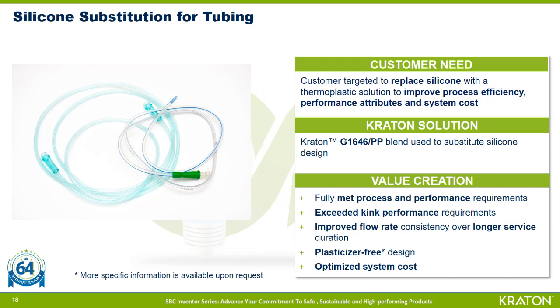These are some of the main reasons why customers are interested in replacing silicone with a TPE solution. And the good news is that Kraton does have a solution in the form of a blend of our G1646 polymer with polypropylene. Tubing made with this blend meets the performance requirements. It is easy to process. It shows improved kink resistance over silicone. Additionally, it also shows better consistency of fluid flow over a long period of time than silicone, and it has an overall improved system cost.